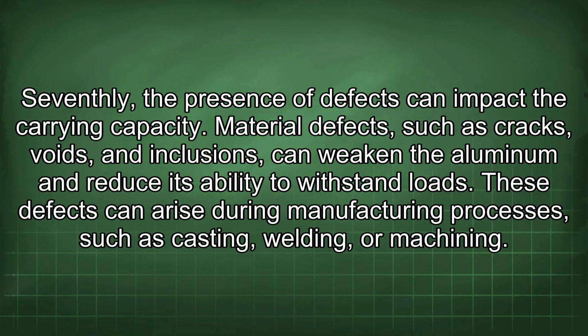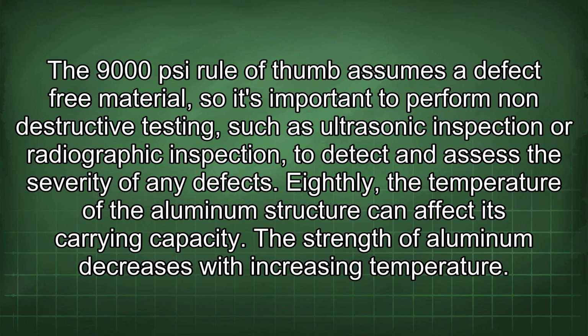Seventhly, the presence of defects can impact the carrying capacity. Material defects, such as cracks, voids, and inclusions, can weaken the aluminum and reduce its ability to withstand loads. These defects can arise during manufacturing processes, such as casting, welding, or machining. The 9,000 PSI rule of thumb assumes a defect-free material, so it's important to perform non-destructive testing, such as ultrasonic inspection or radiographic inspection, to detect and assess the severity of any defects.